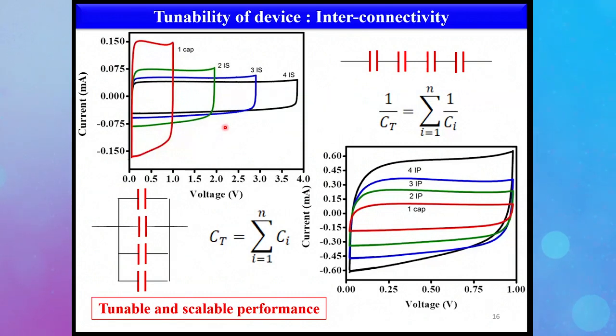Manas Kumar Kundu, hi sir, good afternoon. If you are using ionic liquid, why are you charging for 0.9 volts for a single cell? Is it water contamination? Most of the ionic liquids are hygroscopic, so we need to be very careful about avoiding water contamination. But as you can see from this slide, we have run experiments which can go up to 4 volts as well, and higher voltages also. But when we do room temperature ambient condition measurements, we need to be very aware of the water content in the ambience, because ionic liquids are hygroscopic.